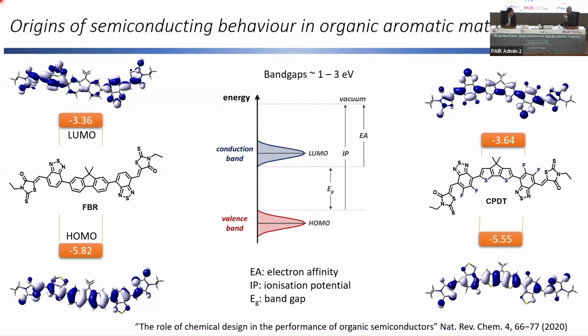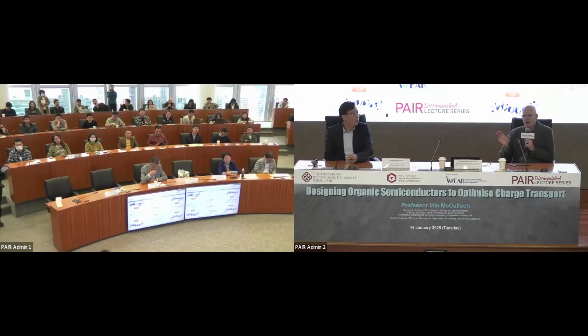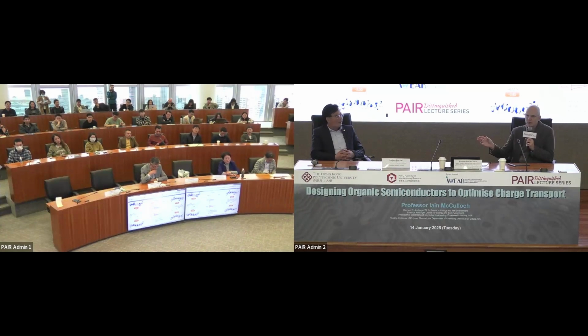So I had a very good slide that would have shown that. I don't have that today, but there are many one electron reactions involving oxidation and reduction. And if you think about the redox chemistry, it's an equilibrium, right? So it's thermodynamics. It's a thermodynamic process, which means it's an equilibrium. And the problem with that from a stability perspective is essentially you can't have your cake and eat it. So if your semiconductor is ambiently stable in the neutral form, when you remove an electron, it's now reactive. So if you have good shelf stability, you have potentially poor in operando stability.